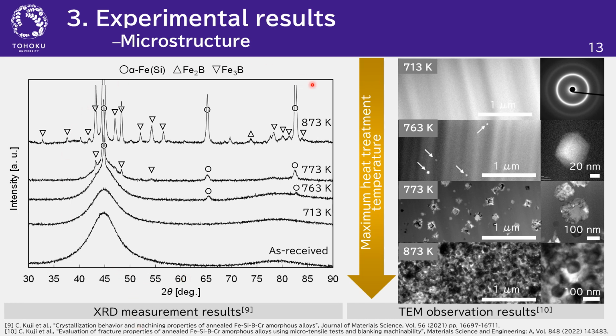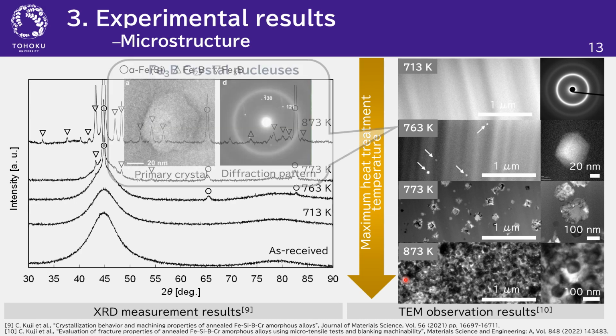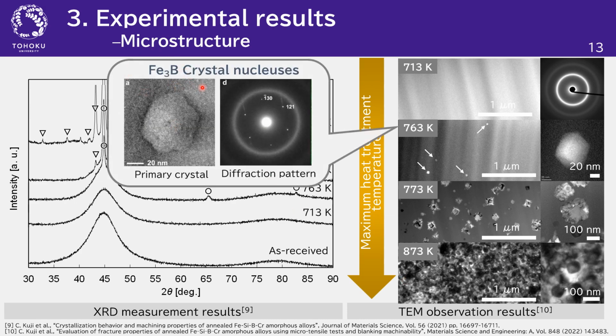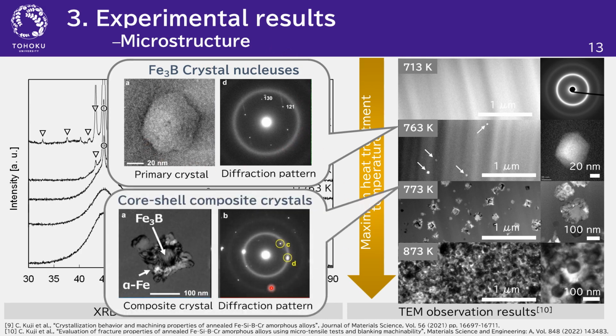The left figure shows the results of XRD analysis and the right figure shows the result of TEM observation. The amount of crystal precipitation gradually increased as the heating temperature increased. It was found that Fe3B was precipitated as the initial crystal, followed by the formation of core-shell-shaped composite crystals, and finally it was completely crystallized.